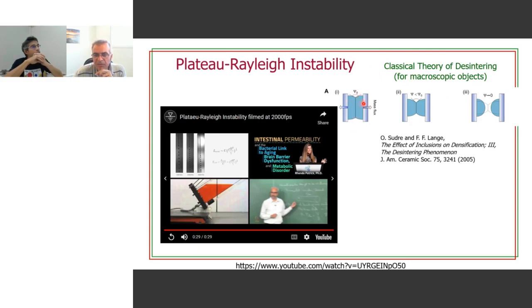So imagine now that you have two nanoparticles or two particles of material, and either by removing mass from the region or by moving these two walls apart, that is, providing tensile stress, you start to shrink this interface between these two nanoparticles. One important quantity to use as a parameter to analyze this process is the so-called dihedral angle. And you see that this dihedral angle starts to decrease until at some point there is an instability. And this instability is very similar in nature, as I said, to the Plateau-Rayleigh instability.